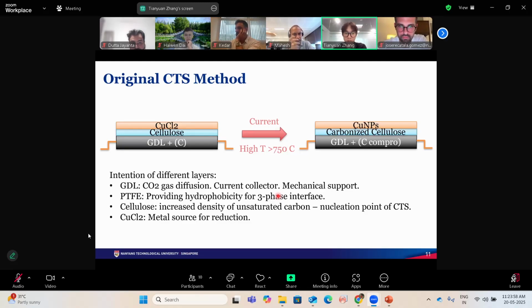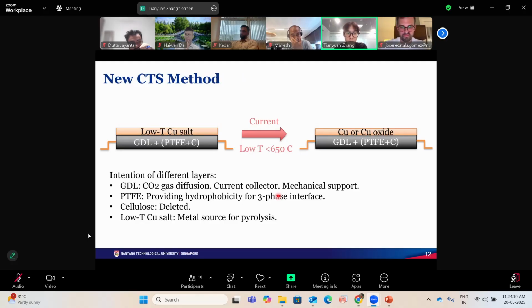It seems very promising, but it is very hard to repeat this sample, because we tried a lot of times to tune different parameters or different conditions of the experiment. So we started to think if we can just remove the cellulose layer, because the cellulose is a big problem in our previous tests. And we developed our new thermal shock method. We start to use new carbon paper with one side already coated with one layer of PTFE, which ensures the hydrophobicity. And we tested the substrate. It can normally work at temperatures not above 600 degrees.